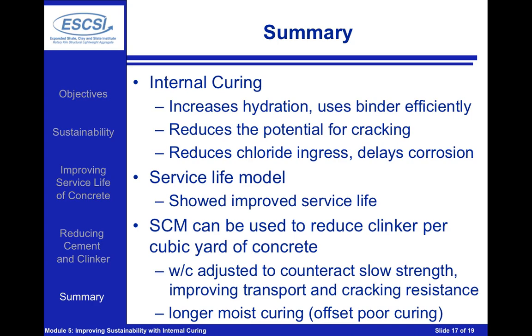The impact on sustainability really comes in two main ways. First, service life models were used to show an improvement in service life in two main ways. The first is by moving from a conventional concrete to a higher performance concrete, we're able to get a substantial improvement in the overall service life. Second, we're able to see benefit by having additional internal curing water and hydrating more of the cement and making it harder for the chlorides to get to the reinforcing bar. Finally, by reducing the cracks in the system, we can dramatically extend the time until the reinforcing bar starts to corrode. In doing this, we saw substantial improvements in the service life of our structures,